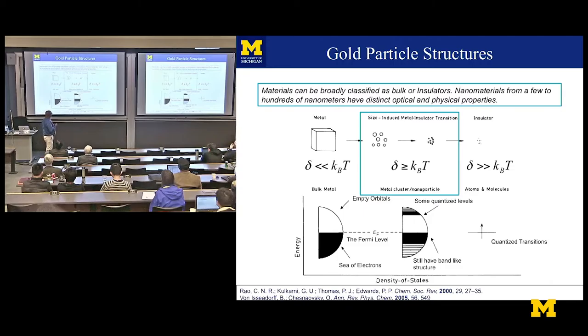But interestingly, nanoparticles are teetering on the edge of this bulk regime, far from the molecular one. And these metal nanoclusters, if you will, are somehow in between, and people didn't understand how to describe this. If you have this sea of electrons and the classical bulk structure, you'd have a surface plasmon resonance, the sloshing of electrons. But if you keep making the particles smaller and smaller, you keep changing the density of states. Is it possible that you could have a band gap opening?